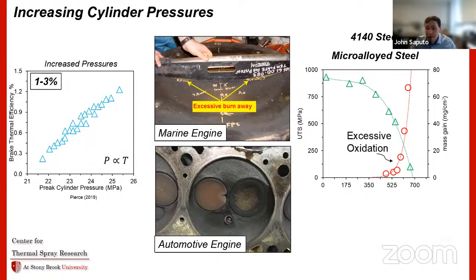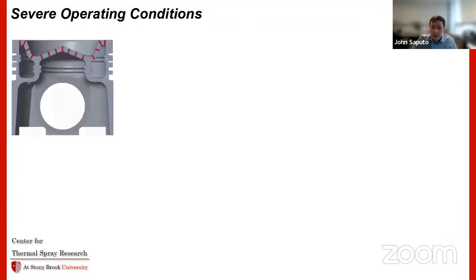So there is a range here where the mechanical properties of these systems aren't really degraded enough to stop them from performing in these systems, but they do rapidly oxidize, which is the issue that people have been running into trying to go to these higher pressures in these systems. So that's sort of the thing that we can drive down and hope to make go away with coatings.